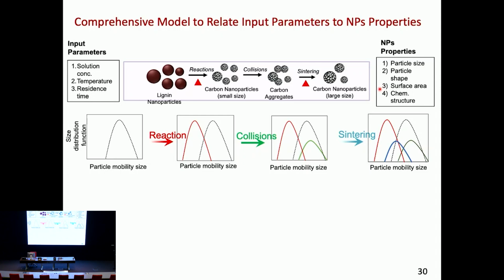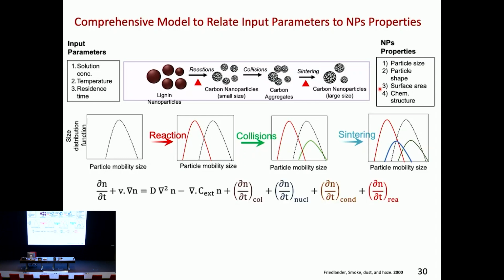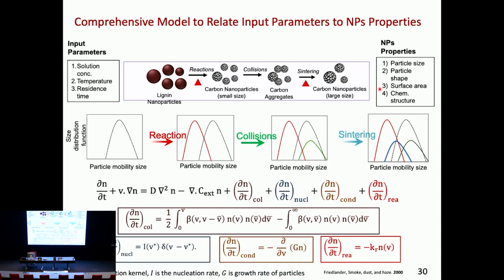But then when I collide them, they again shift to the right, the green size distribution. And then when I sinter it, I get some kind of shrinkage in the particle mobility size shown by that blue size distribution. And of course, I want to understand this very carefully so that I can use it. So I bring back my good old equation with the right terms. I won't go through it now. You've got some exposure to that.